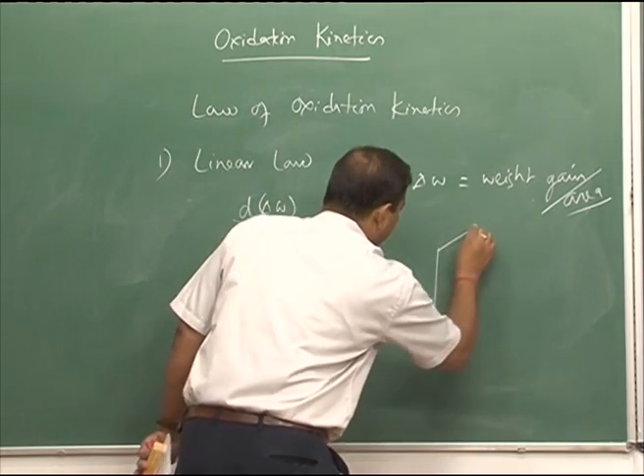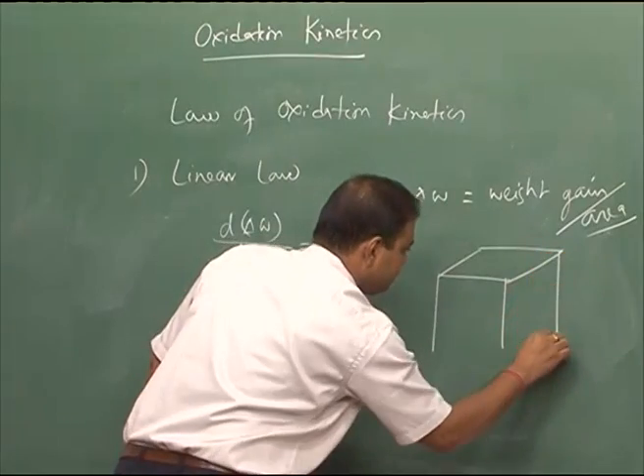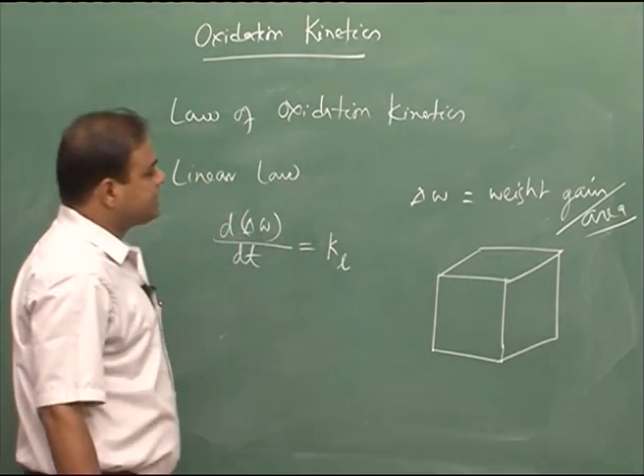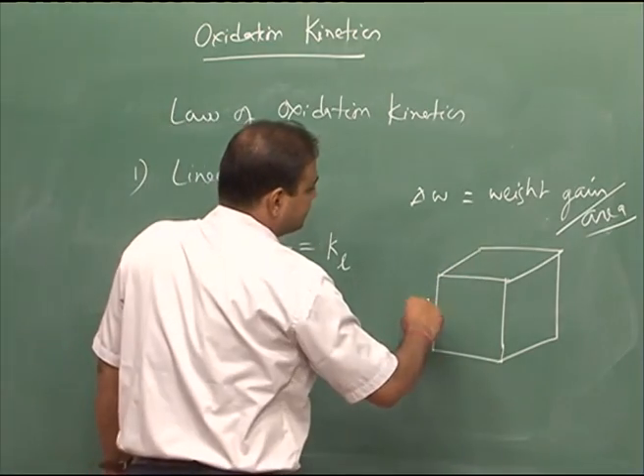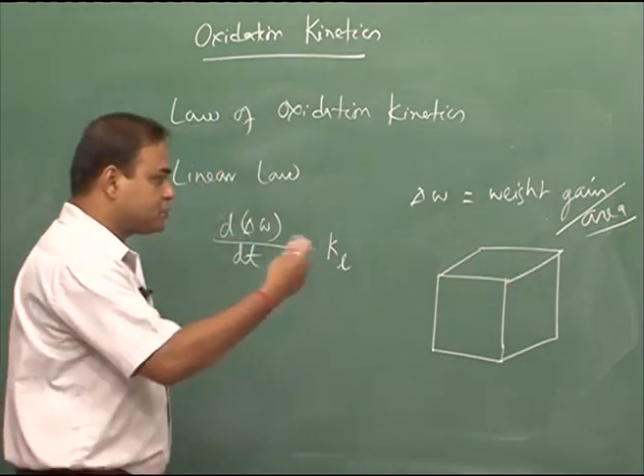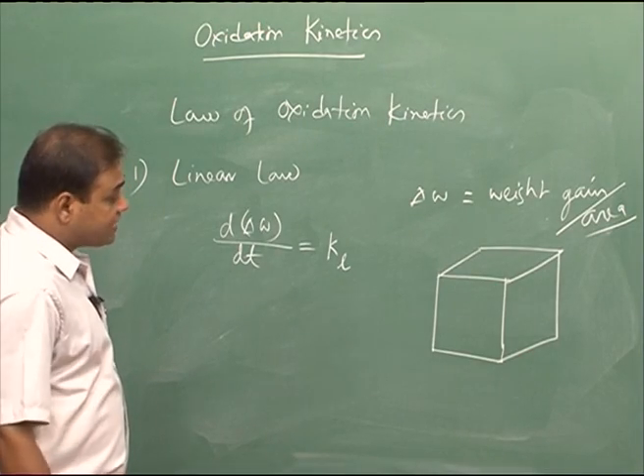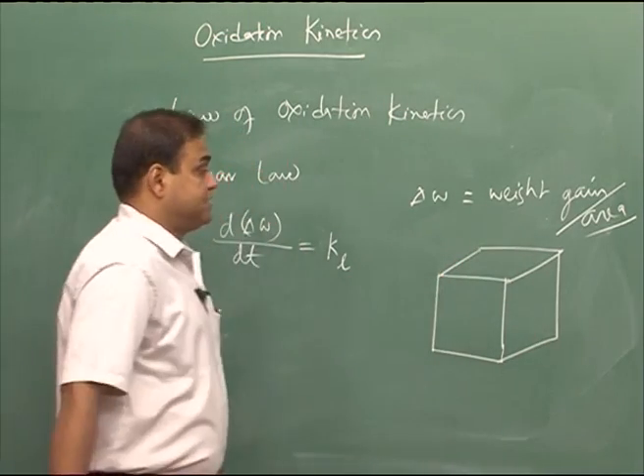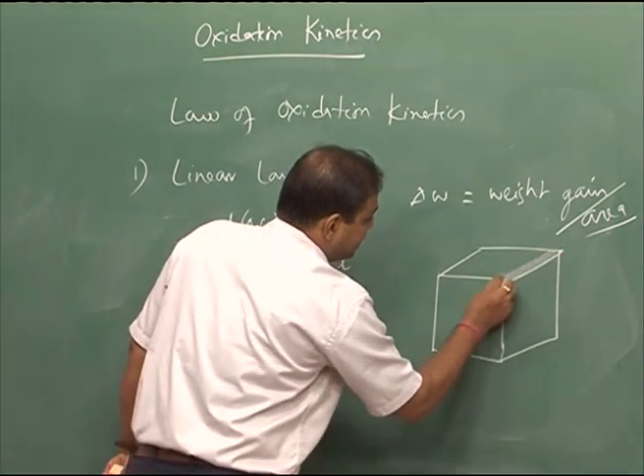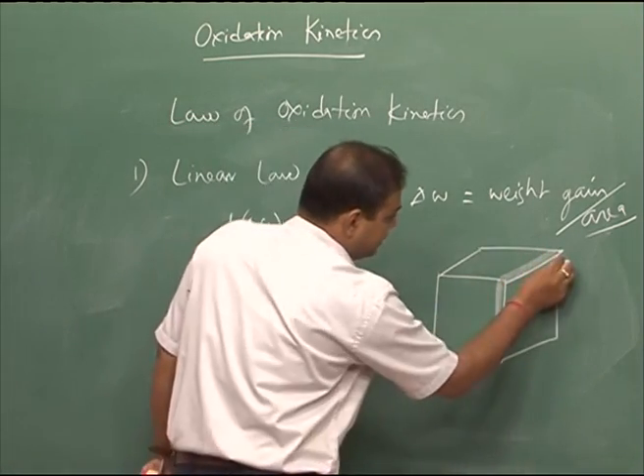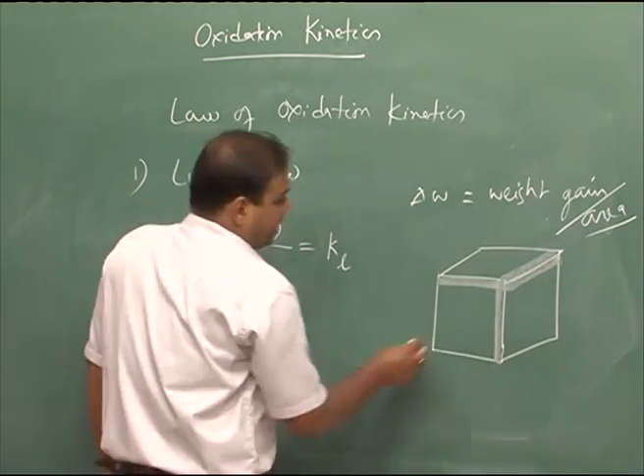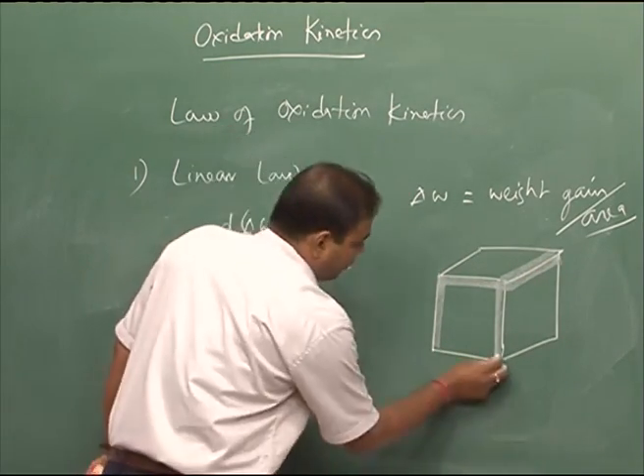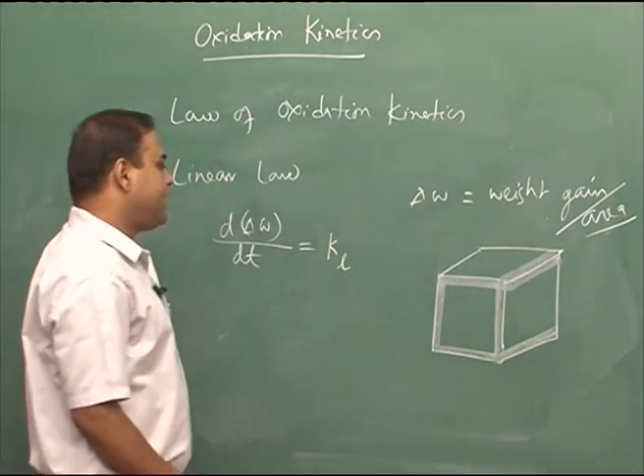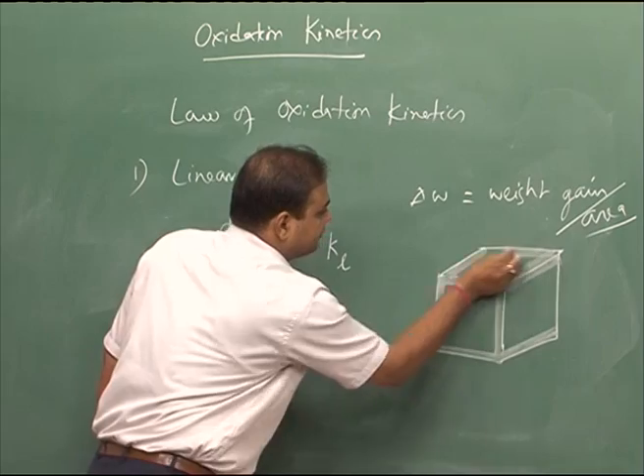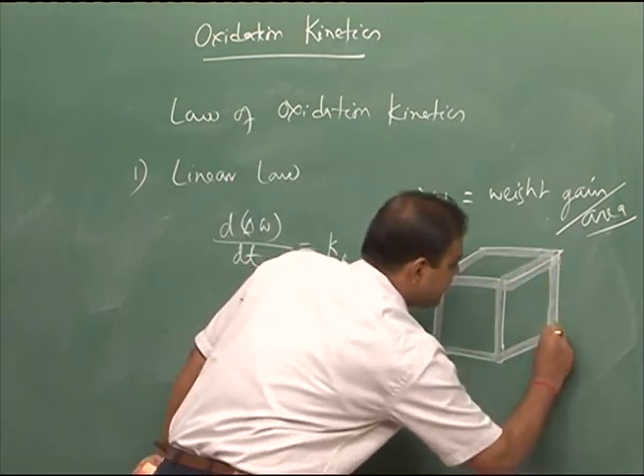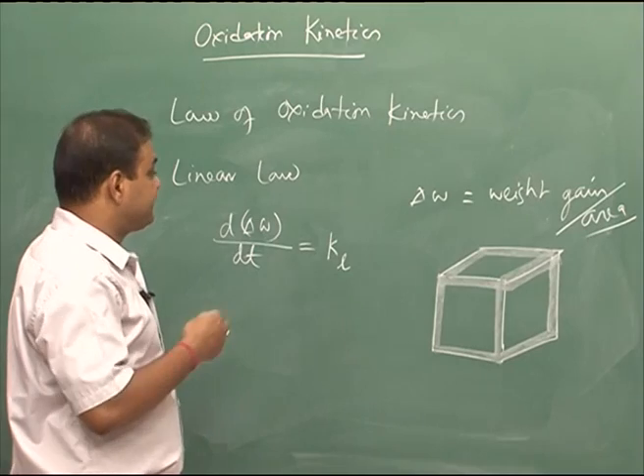Let us say we are considering this cube of metal which is getting oxidized. Whenever we see the oxidation process, actually the 6 faces are exposed to the oxygen, and those surfaces are getting oxidized, and on the surface gradually you have oxide growth. Similarly, this way you can have oxide growth, and this way, or this way. So, like that 6 surfaces are getting oxidized, and the thickness of the oxide is gradually increasing.